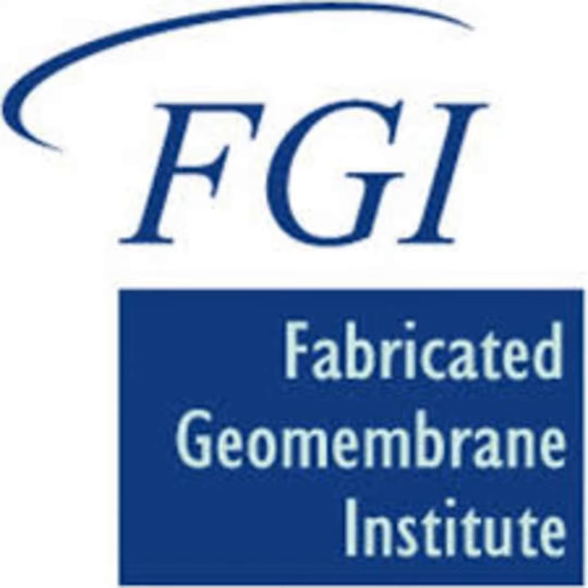So whatever project you're going to be working on, whatever material you have, you definitely want to evaluate that, because I've seen some spikes that are pretty rounded off and low, that have quite low interface strength, and I've seen some of that blown film that is quite grippy and has some really good strength. So definitely depends, and I wouldn't want to say one or the other, but in my experience, the ones I've worked with, I've seen some really nice microspike geomembrane. I don't know if you want to add some comments in on that as well, Tim.